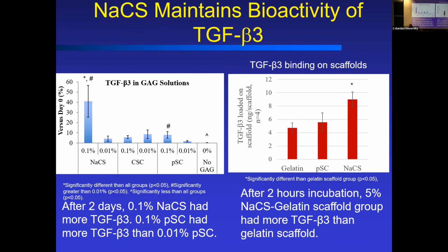So we look more carefully again at mechanism. As I mentioned, that degree of sulfation can affect protein interaction, and in particular, the TGF beta, which is a driver of chondrogenesis, that growth factor. So we see again with the fully sulfated cellulose, as shown here, you get high amounts of that TGF beta interaction or binding in solution, as well as on the scaffold, so incorporated into the scaffold. That's shown here as well.